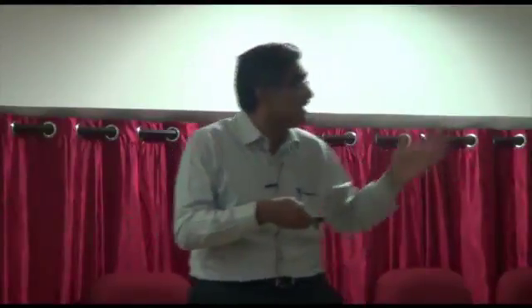To verify this, we also made some magnetoresistance measurements and collaborated with IIT Bombay for this. Professor Dhar works on low temperature, high magnetic field measurements. We did some and showed that there is a presence of weak localization, which can give us this high mobility. Now we are looking at Shubnikov-de Haas oscillations, which will confirm whether these are 2D electron gases or 1D electron gases. We are working on that, and we are also collaborating with my colleague Professor Jawaharlal, who is doing some theoretical DFT calculations to find out whether it is a feasible thing or not. So we are trying to understand this.